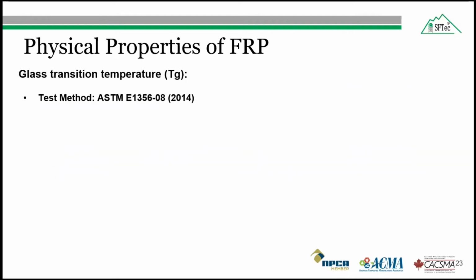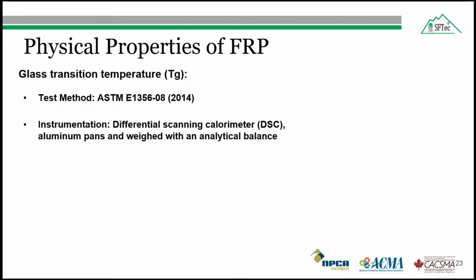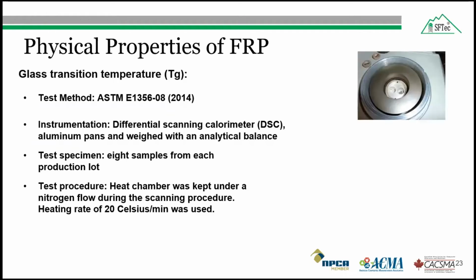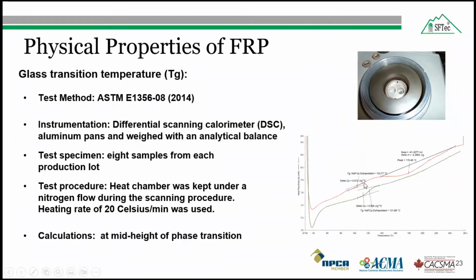The fiber reinforced specimens for glass transition temperature were tested in accordance with ASTM E1356, and a differential scanning calorimeter was used with aluminum pans, and the specimens were weighed with an analytical balance. For each production lot, 8 samples should be tested, and the small size specimens were cut and placed in the heat chamber, which we can see in this figure. This is the heat chamber, which was kept under a nitrogen flow during the scanning procedure, and a heating rate of 20 degrees Celsius per minute was applied. The value of glass transition temperature was taken at the mid height. From this graph, you can see that it was taken from the mid height at the transition phase. When there is a transition, we take the value here.